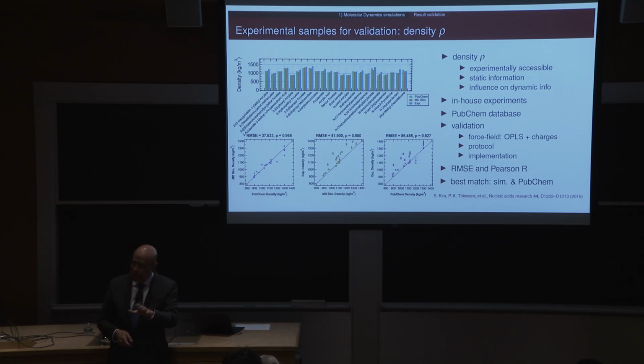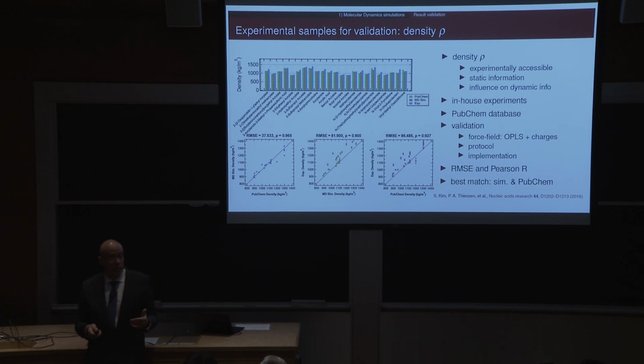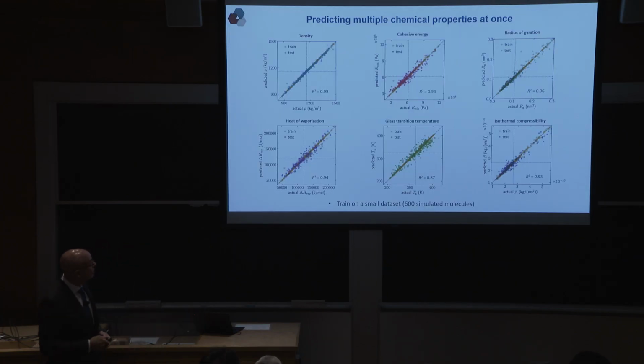And what is amazing about this type of work now is that when you don't have the data, you can actually generate libraries with hundreds of entries using simple simulations with simple force fields. It goes very quickly, and those force fields have become so good that when you compare properties to experimental measurements, they really agree with each other. You can train them. So we do have a database, and you can actually create those databases for any family of molecules that you want at this point.